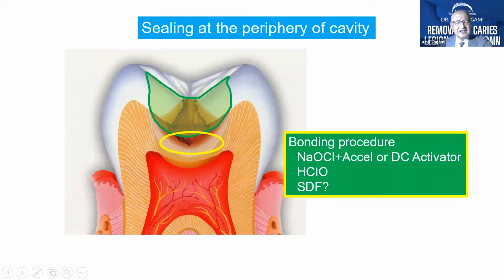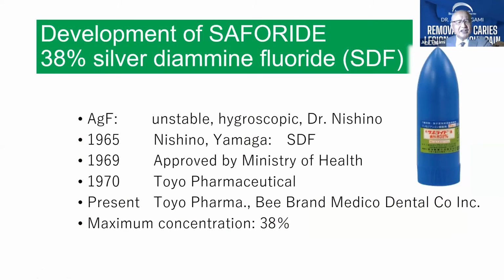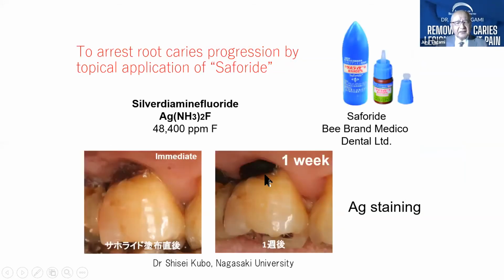And sometimes I gradually start to use silver diamine fluoride. This 38% silver diamine fluoride is widely used in Japanese dental treatment for many years. And it shows a very excellent performance to prevent caries as well as arresting the active lesions. However, the color of the region becomes very dark, black or brown. In the very highly advanced aged society, this kind of application of SDF is very strongly recommended. Of course, the color of the region becomes very black, but this is very effective to arrest the lesion.